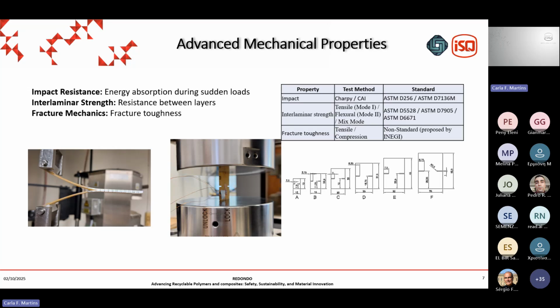The interlaminar strength is another property that is quite important for laminated composites, and involves the determination of the strength of the adhesion between layers, different layers of fibers that are used for those composites. And that usually involves the introduction of a defect, usually by inserting a Teflon or other similar material between 2 layers of the material at mid thickness, and then trying to open that pre-existing defect to measure and study its propagation across the material.